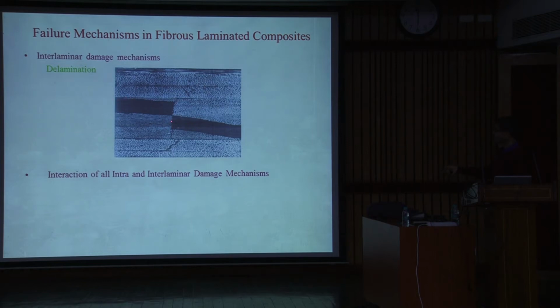And this one shows the interaction between intra and interlaminar damage mechanisms. There was a delamination, it was propagating like this, then it sees that now it cannot propagate along this interface. It has found that there is a weak direction in the ply itself. So the crack, which was the interfacial crack or the delamination that was growing along this, has moved in the thickness direction. And it goes to the next interface. Then again it sees that the interface below this is weak, so again it has propagated like this.